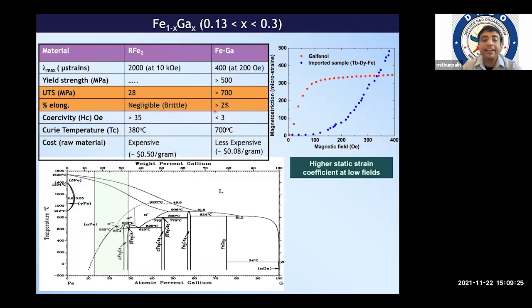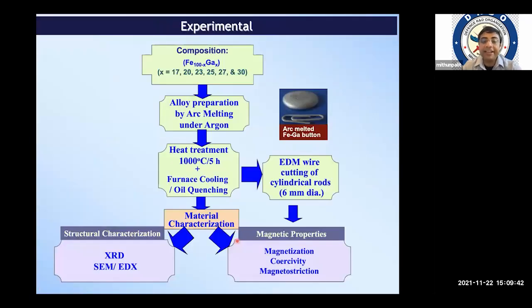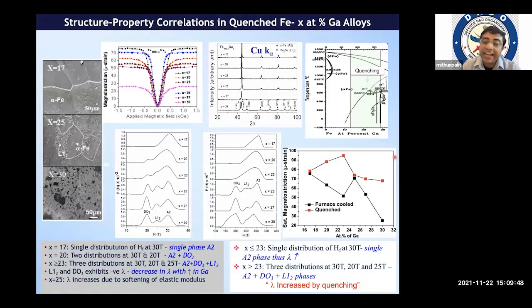We cannot expect the ductility of a nickel-based superalloy or steel or aluminum alloy. And it also has a lesser coercivity, so that you can see the initial slope of the curve. This Galfenol material has a steeper slope, so it can be a better actuator material. We developed this material through the arc melting route followed by several heat treatments. And what we found is that adopting certain furnace cooling and quenching, after heat treatment at 1000 degrees C, if the material is suitably quenched, then it gives a better magnetostrictive performance than the slowly cooled material.